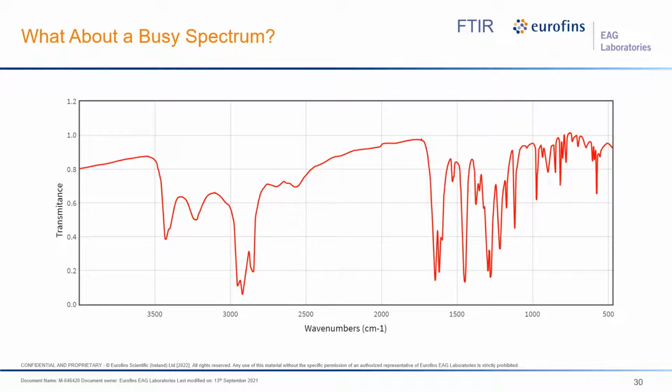If you have a very busy spectrum, then what do you do? And this one is a basic spectrum. I just use it as an example, but it's not a complex spectrum. This one is coming from my database, caffeic acid. If you search our database, you get a 100% match. So what we normally do is a library search, and if it's not going to match, you can search several different functional groups. I like to search the region we call the functional group region, the one from about 1800 to 1000 wavenumber or somewhere there. These are usually characteristic peaks.